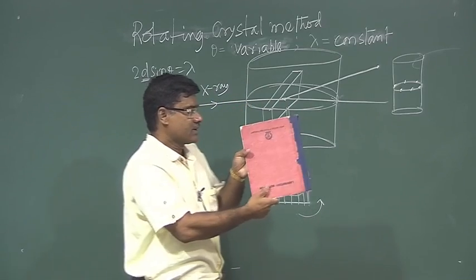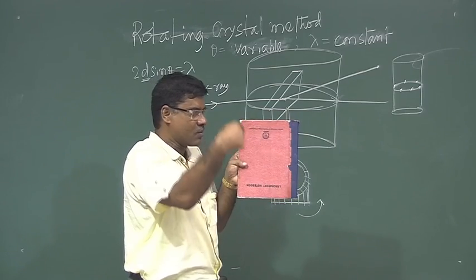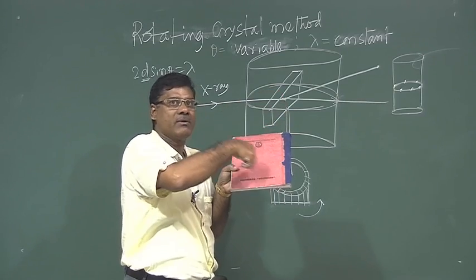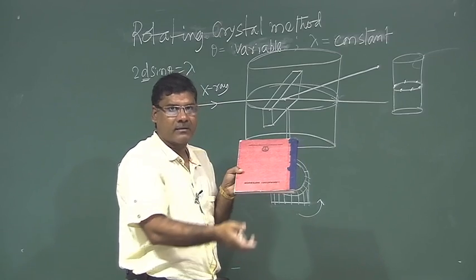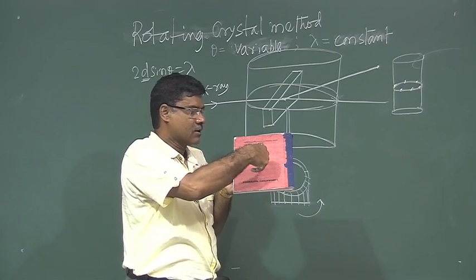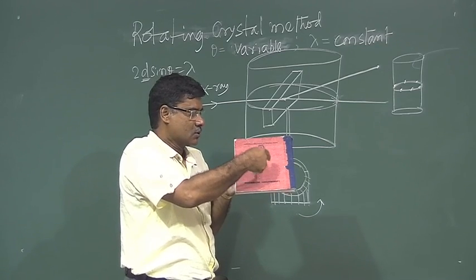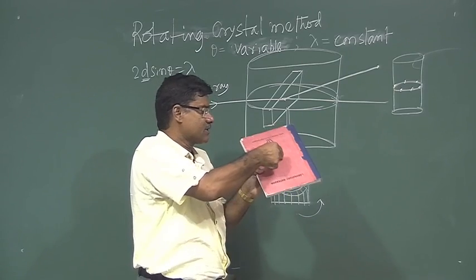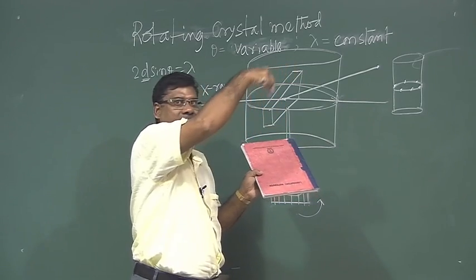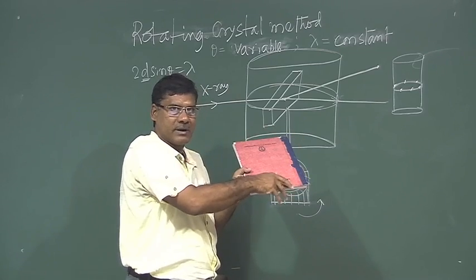Okay. So if you take another axis, now this axis is, say, this, it is normal to the X-ray. Now, another axis if you consider this way, so this is another axis. So again this will be a zone axis for a different set of planes. Okay. Now, it is not normal. Okay. So X-ray is not normal to this axis. Okay. It has some angle. So the reflected beam, whatever you will get, will be just with some angle, right. So it is up. So again on the upper side you will get another circle, and spots on that circle will represent the planes of this zone having a different zone axis.